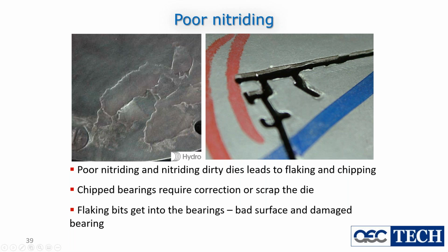I haven't seen that very much because I believe with systems like Nitrex and other people who have automated nitrogen gas nitriding, we don't go that crazy anymore. Back in the days when these things were just chucked into a bath of molten cyanide and left until lunchtime or dinner time to come out, there wasn't the same process control. But poor nitriding and dirty nitriding leads to flaking, chipping, chipped bearings, and flake bits that come off the die, like the left-hand side. They can actually get into the die bearings and cause problems themselves as abrasive particles.